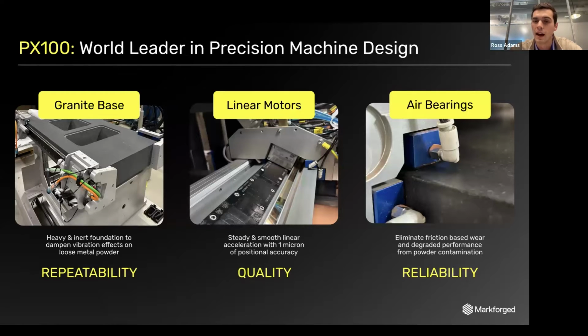And then air bearings, this is very low wear, very low friction, but more importantly, when we talk about loose metal powder, the risk of contaminating that powder into a ball bearing, that's going to deteriorate your results over time. So our platform is entirely suspended by air, and that allows it to be running with very high uptime. We have printers in Sweden that have been running for over 10 years now, and they're still making production parts.